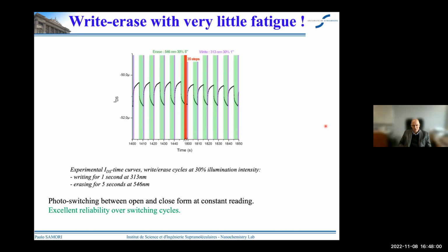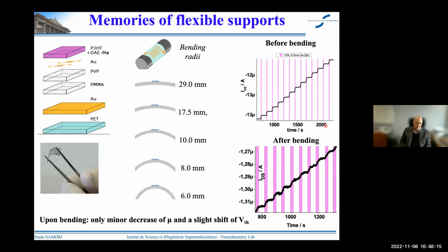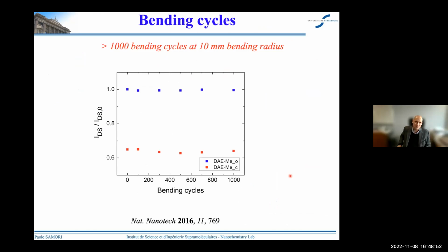There is a larger and larger request of supporting electronic devices on flexible foils because of the potential for having, let's say, wrappable and wearable devices. And so that is what we have been doing with the same blend and essentially supporting this on a different type of geometry of the device, which is based on a polyethylene support. I don't want to enter inside the details. You can see that we can make bending at different radii. For example, you can see that before and after bending, this kind of light responsiveness is retained. We could also retain it with a very small decrease of mobility and very slight shift of the threshold voltage. We also found a referee that asked us to do some bending cycles.